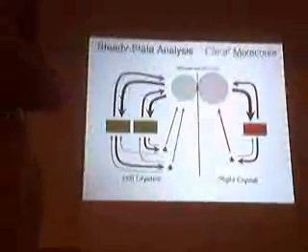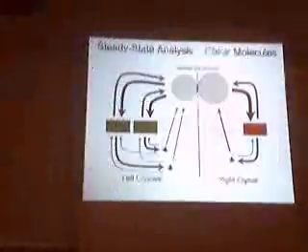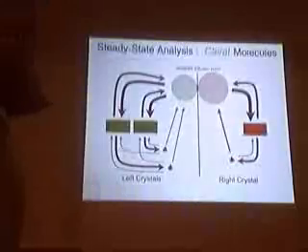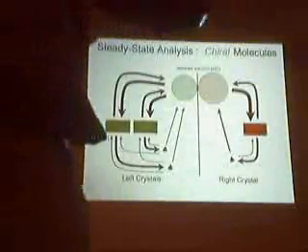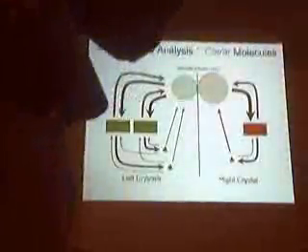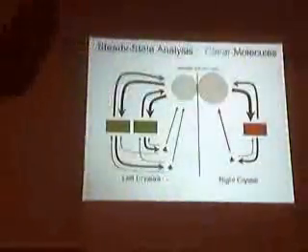And people often talk about a solution being supersaturated or undersaturated. But that's always a relative term. Compared to what? Compared to crystals of what size? So in steady state, the smallest crystals are always dissolving, and the largest crystals are always growing. But as the smaller crystals go away, the concentration in solution slowly drops. So bigger and bigger crystals become stable, and smaller crystals become unstable. You keep raising the ceiling or the floor, right? And that's what I think of as Ostwald ripening, the steady growth in size.